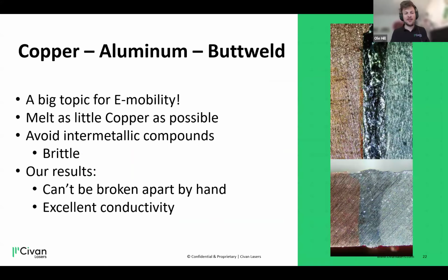And finally, coming to the crown jewel of welding, which is dissimilar materials. Of course, we also tried this topic out, because I always say this Civan laser shows its strength where other lasers have their limits. In this case, it is copper to aluminum, and if you have tried it, it's usually very brittle. Sometimes you cannot even test some material properties because the samples already fall apart when you take them out of the jig. So this is the real challenge of aluminum to copper welding.